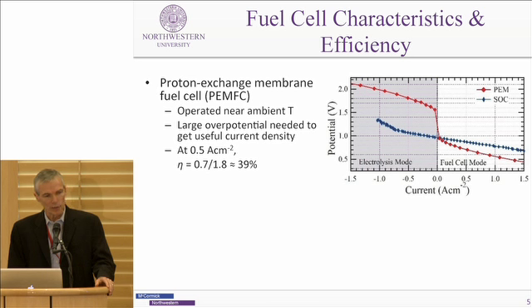If you go to the right here, you're in fuel cell mode, and you're dropping below the Nernst potential, drawing current through the cell, and operating at a lower potential. If you go in this direction, then you're operating in electrolysis mode. And you would be putting in energy and producing a fuel in that mode. Okay? And the first one I've shown here is basically a low temperature fuel cell, proton exchange membrane fuel cell. That's the red curve here.